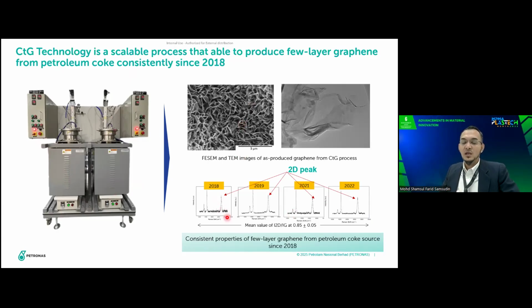The way we monitor the quality of graphene is using the Raman spectroscopy technique, where we look into this 2D peak that I highlighted with this arrow line. From this study, we can see the quality of graphene that we produce from our lab here is quite consistent from 2018 until 2022. And for the poor type of graphene, normally the 2D peak is very low. All right.